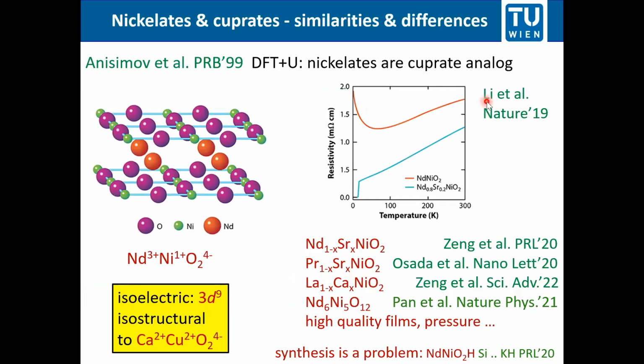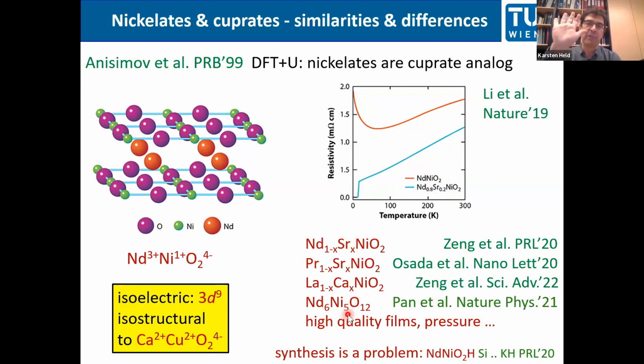4 years ago, Danfeng Li, Harold Hwang, and co-workers discovered a new class of superconductors, nickelates, and that is the figure from their original paper. So they have 20% strontium doping of neodymium nickelate, and they see a superconducting transition at 14 Kelvin. By now, a couple of other groups have synthesized very similar nickelates. There are about 5 groups throughout the world that can synthesize these nickelates successfully, even superconducting ones, but it remains very difficult to synthesize a superconducting nickelate.